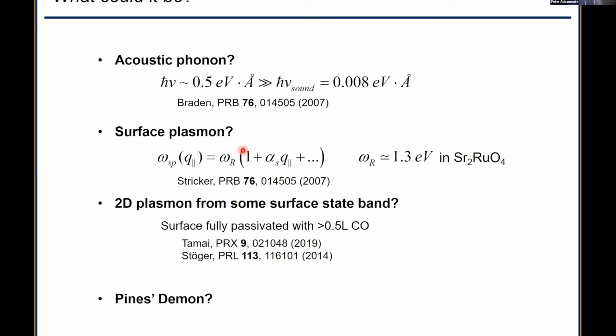That point has been measured in strontium ruthenate by Dirk van der Marel's group, and it happens at 1.3 eV. So it is not anywhere near in the energy scale of anything that could explain what this mode is. It turns out strontium ruthenate also has a surface state. Surface states have been known to create gapless collective modes on surfaces, just because a conventional plasmon in 2 dimensions is gapless. But we took measures, turns out not deliberately, by accident, but we took them nevertheless.